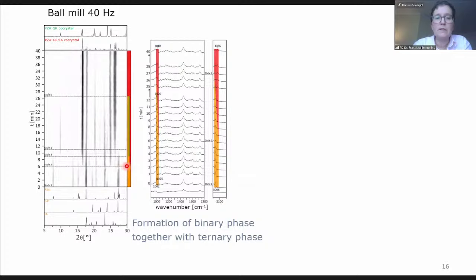And then we see here, shown in red, the formation of the product, which is the only phase we end up with, so the ternary co-crystal. But in between, you can see with this little line here that belongs to the binary compound, we see the formation of a binary co-crystal. Here the Raman data is shown, so that is not differentiating between binary and ternary compounds, but we can nevertheless see that we have some formation of a multinary co-crystal.